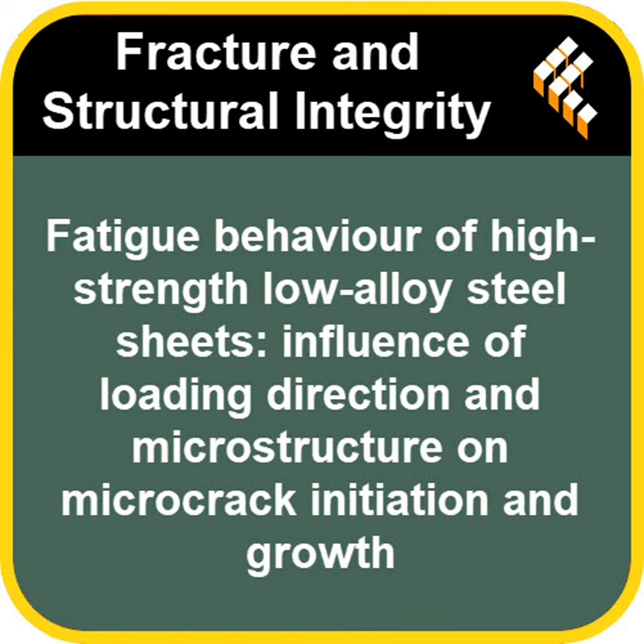Okay, so if it wasn't phase differences, what caused that bilinear behavior, that shift in failure mode? It seems to reflect a change in what's dominating the fatigue damage process. At those lower plastic strains, deformation is quite localized. So fatigue life is mostly determined by crack initiation, how easily those first tiny cracks start. Where the first domino falls, basically.